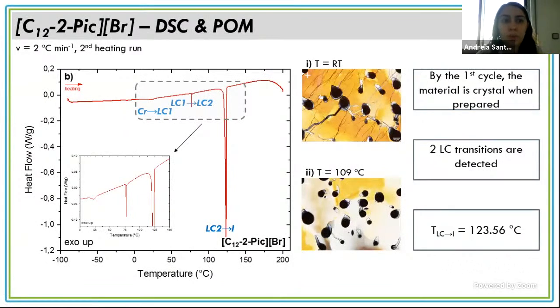For C12 2-picolinium bromide, in the first heating cycle, the material is crystal when prepared, and in the second heating, 2 different LC transitions with low enthalpy were detected. The first one at 25 degrees and the second one at 75. The isotropization was at 124 degrees.